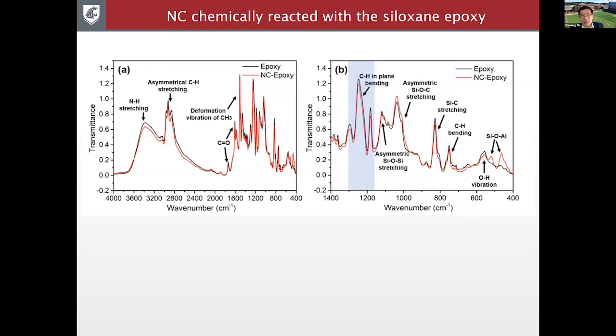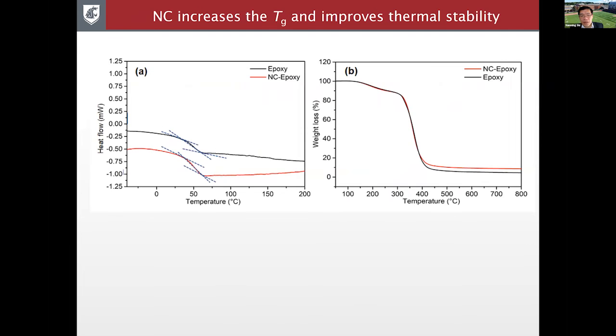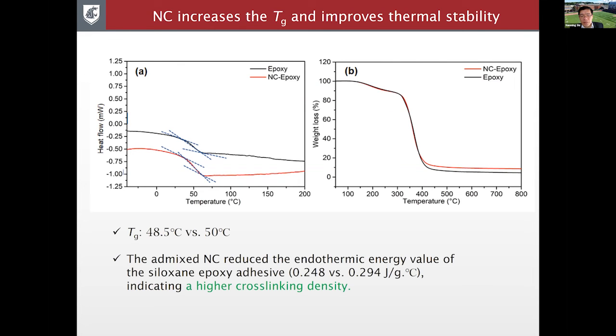And also the Fourier transformation infrared spectroscopy confirmed the nanoclay chemically reacted with the siloxane epoxy resin. And the nanoclay also increased the glass transition temperature and improved the thermal stability of this epoxy. For instance, the glass transition temperature increased from about 48.5 degrees Celsius to 50 degrees.